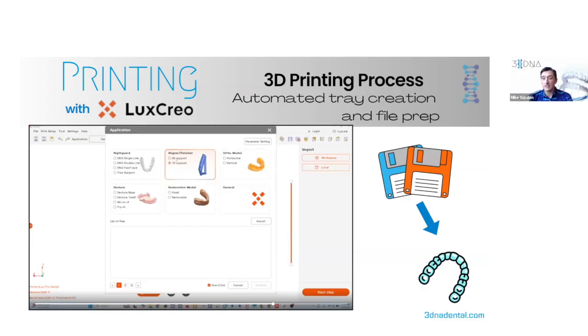They're definitely successful at moving teeth. They did come out with a newer resin that is less flexible, so a higher glass transition temperature in their most updated resin. From what I understand and from the cases that we had worked on, there was some difficulty in finishing cases when your flexibility was that high. When you're not trying to move as much, it's like the difference in the force application at the interproximal, and you're really trying to close those gaps at the end. It turned out to be quite difficult with those really flexible resins.